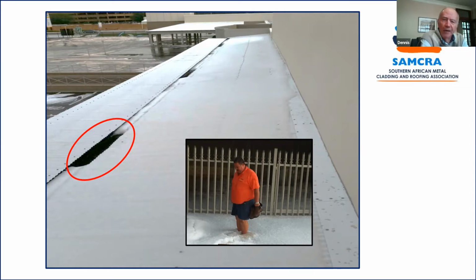The other thing is that hail doesn't tend to slide off a roof until you start to get around a slope of 26 degrees. So anything less than 26 degrees, it's just going to sit on that roof. And the problem again arises there is that it freezes. It freezes rather rapidly, but particularly with an insulated roof, you get that layer almost like what's underneath a glacier. The interface layer between the hail and the cladding is where the first lot of melt takes place, and you then get flooding of the pans.